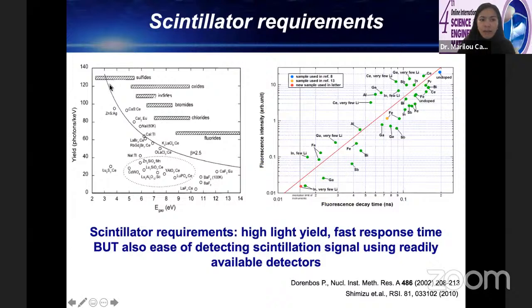So there is a lot of research going into materials for scintillators, and there is already a large number of existing scintillators. This graph shows just some examples of the scintillators that have been developed, but still there is a continued search for scintillators due to the requirements imposed by various applications, which a single scintillator cannot satisfy. This figure here on the right shows two characteristics that are important in scintillator development. Of course, luminescence intensity. The scintillator should have enough light output in order for detection to be possible. But at the same time, fluorescence decay time or luminescence decay time, or the response time of the scintillator, is also important. We can see here that there's a trade-off between intensity and decay time.